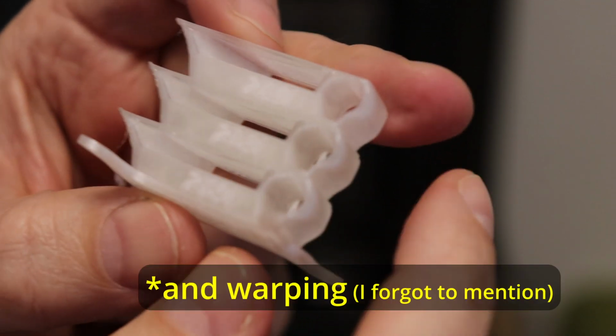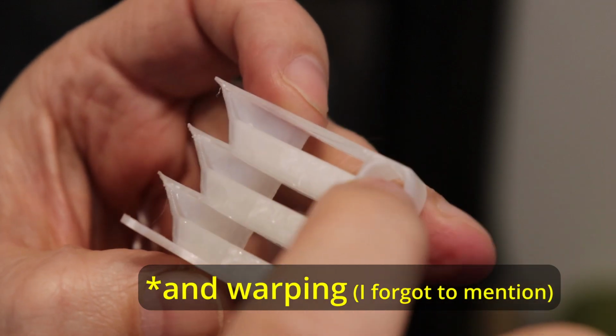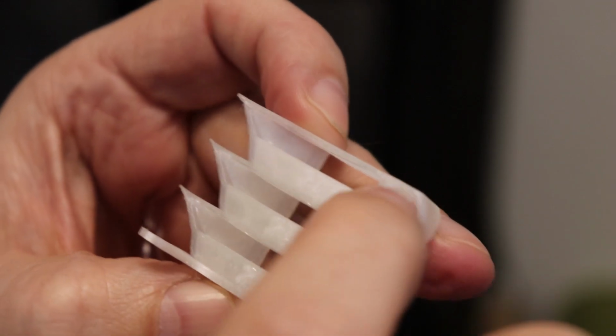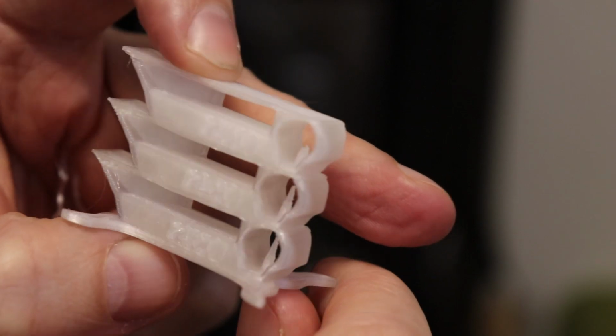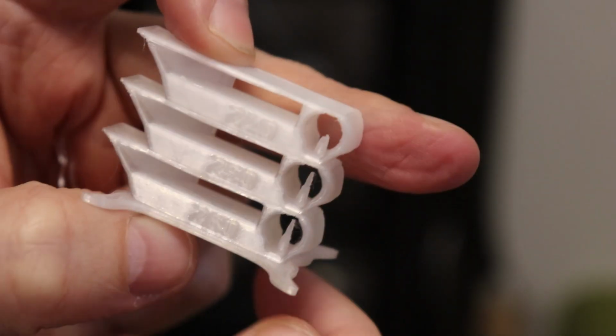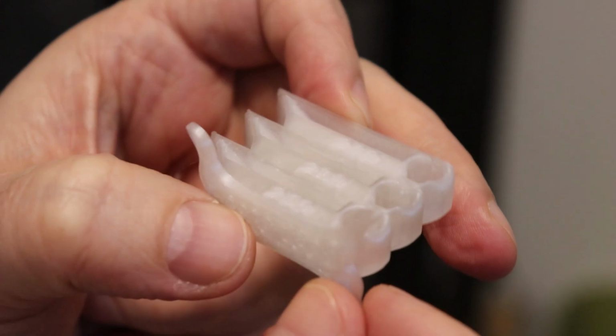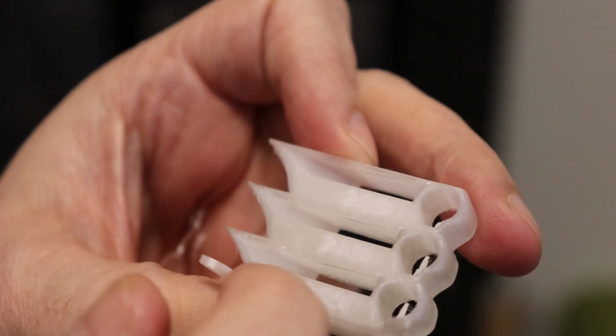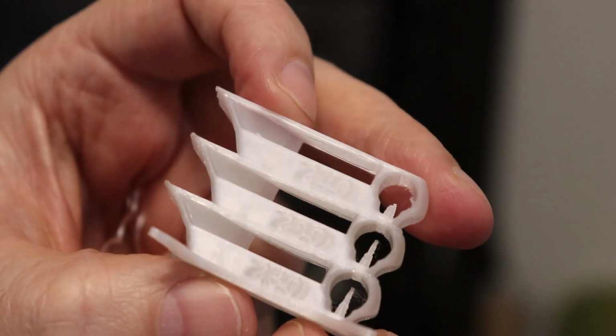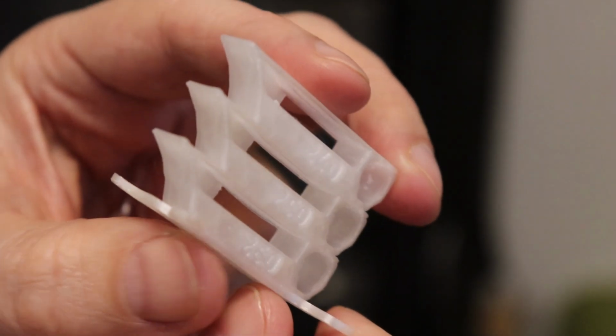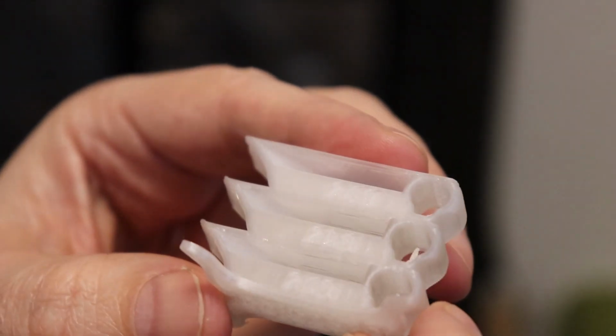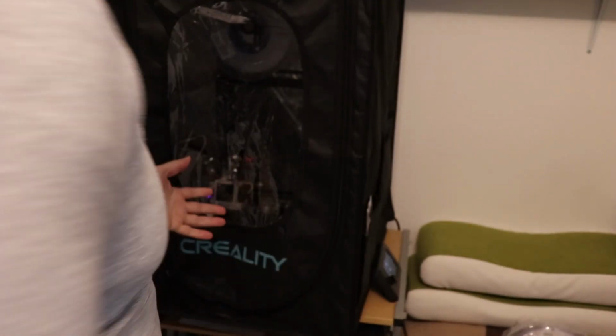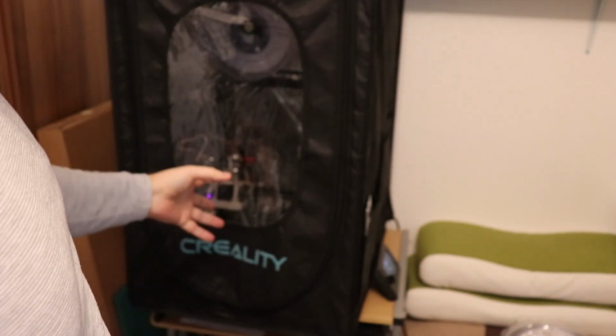The only problem I can see is that at 240 degrees Celsius this candle for the stringing test was broken. I'm not sure what caused this because I wasn't here to supervise it. I was quite sure that it would print correctly after I saw the first two elements. So I printed everything at 250 degrees Celsius. And the last group of test specimens from polycarbonate.